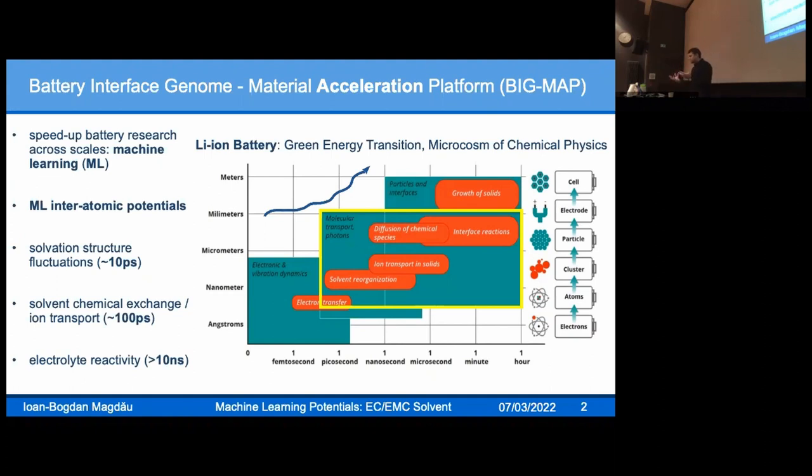Some of the relevant phenomena are solvation structure fluctuations around ions at a 10 picosecond timescale, solvent chemical exchange underlying ionic transport at one order of magnitude higher, and eventually electrolyte reactivity and the formation of the solid electrolyte interface that is of paramount importance for battery efficiency.